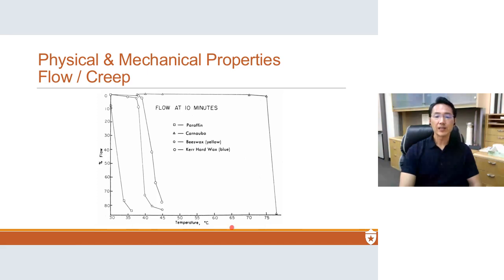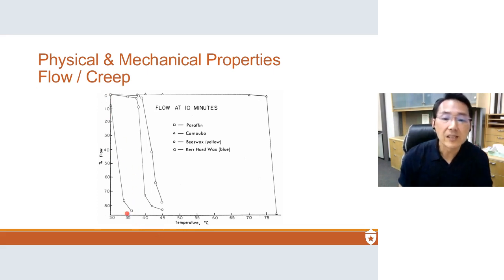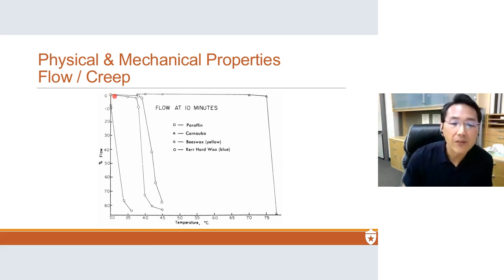So as you increase temperature, the percent flow increases drastically for waxes. In this case, it's paraffin, and as soon as you pass, what is that, 30 degrees, it just flows really quickly. And then you have carnauba on the other opposite end. It just doesn't flow until a very high temperature, and then you have beeswax. One reason why it's used in the dental waxes is because if you look at the temperature, once you hit about 40 degrees, then it starts to flow.